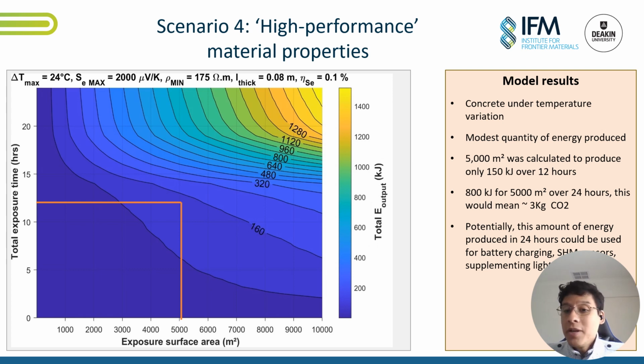But what happens if we further enhance the Seebeck coefficient and reduce the electrical resistivity on a real temperature regime? We can increase the energy output from 60 to 150 kilojoules in 12 hours, or 800 kilojoules in 24 hours, at 5,000 square meters. It would mean an offset of 3 kilograms per day, over 1 ton per year. If we increase the area that is going to be exposed to the sun, we're going to increase the energy output and reduce this further.